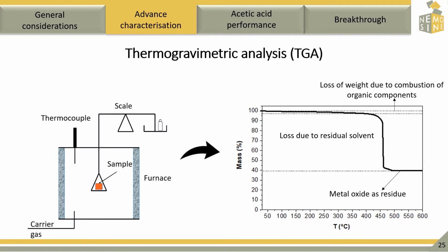Normally, when MOF materials are subject to very high temperatures, they tend to decompose or collapse. However, the removal of water and organic compounds from the pores of the material is important, and to achieve their full potential, most MOFs need activation. And this technique is a perfect method to evaluate how temperature will change and alter our material.